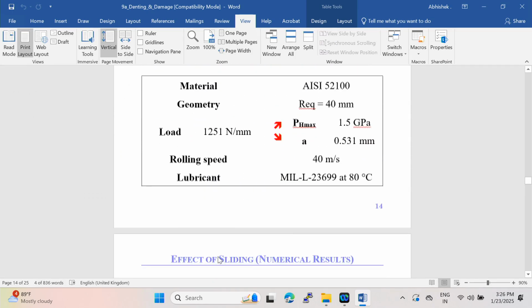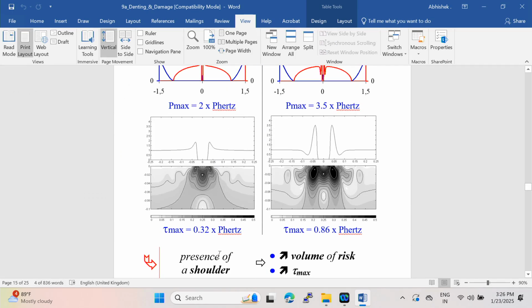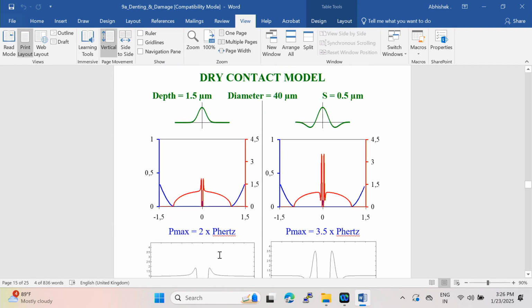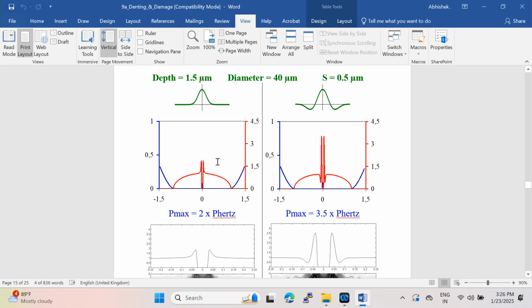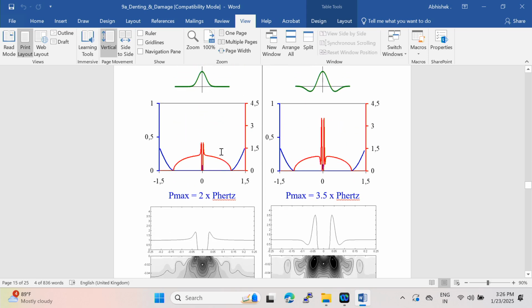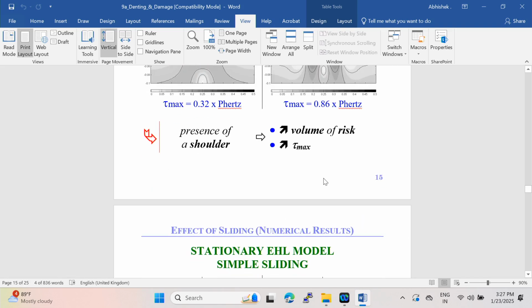Okay, these are some numerical experimental data. These are the effect of the shoulder. You can see on the left a dent without shoulder. Then the peaks of pressure are very small, and a dent with a shoulder which is not very high, 0.5 micrometers. You can see a very huge magnitude for the peak of pressure. Typically here, the peak of pressure is about 2 times the Hertzian pressure, and here the magnitude is about 3.5 times the Hertzian pressure due to the shoulder. Then the shoulder is a problem for dents.